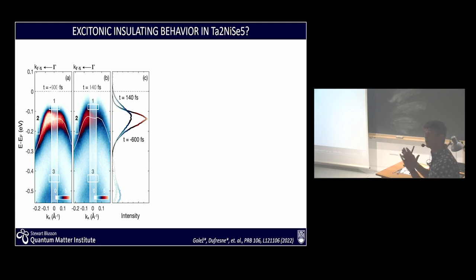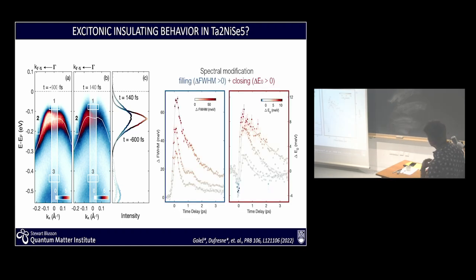So small change of gaps, but big change in the width. Basically, the change in the width is a factor of 10 bigger than the shift in peak position. So once again, the action appears to be in the lifetime of a system. I can go through the detail here, please ask me, but this is the message. The lifetime is what really changes here.